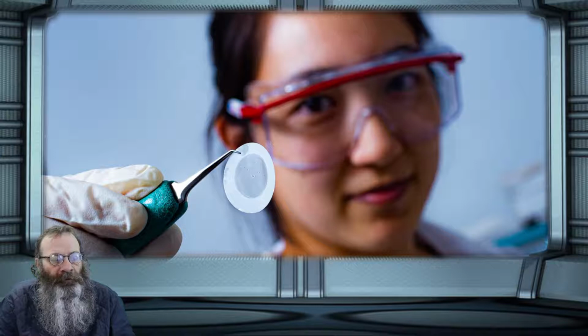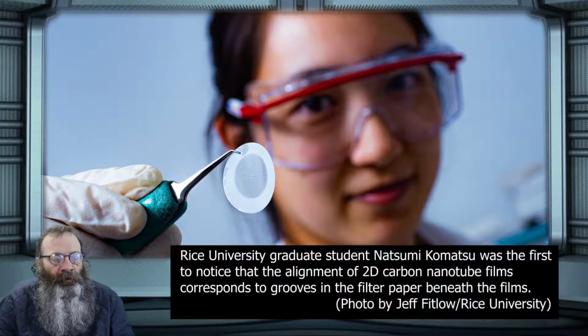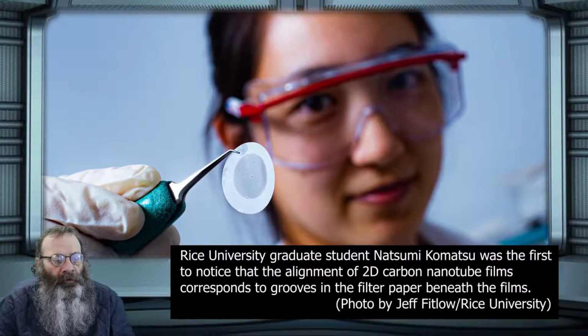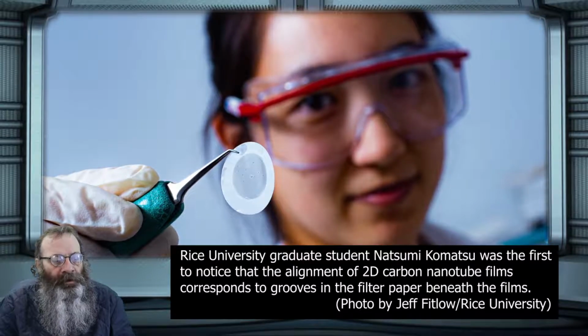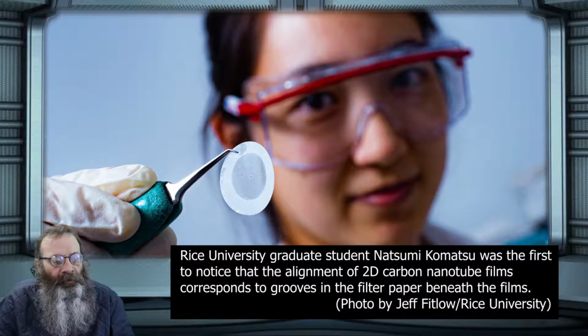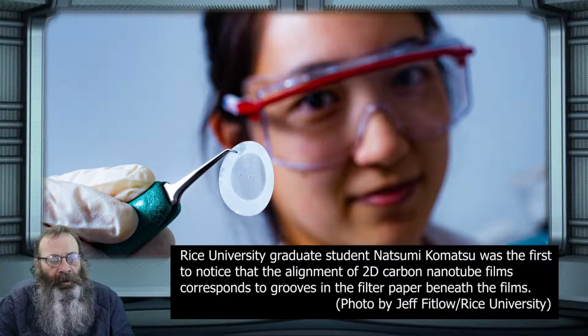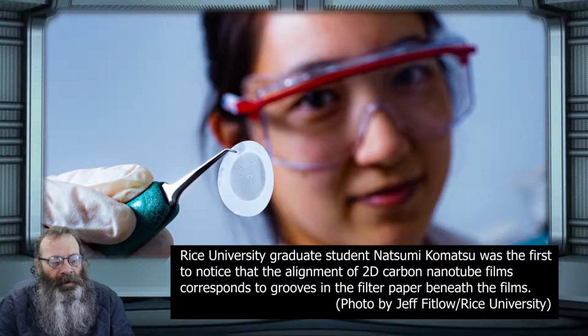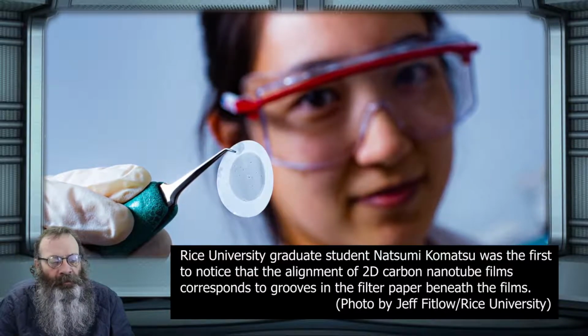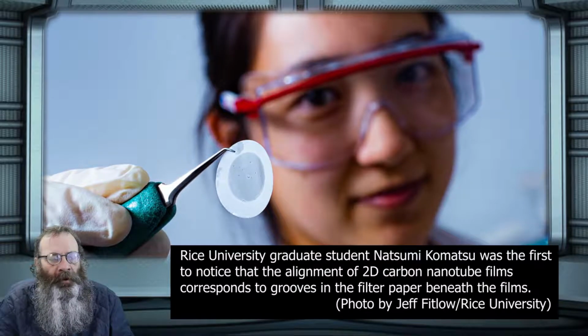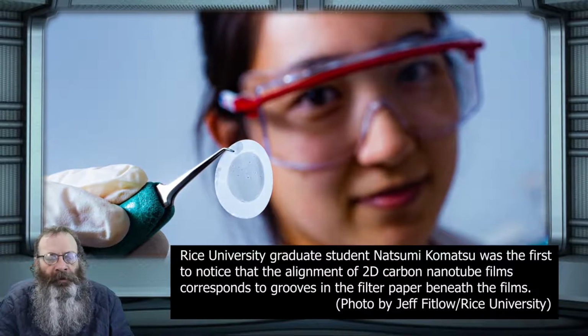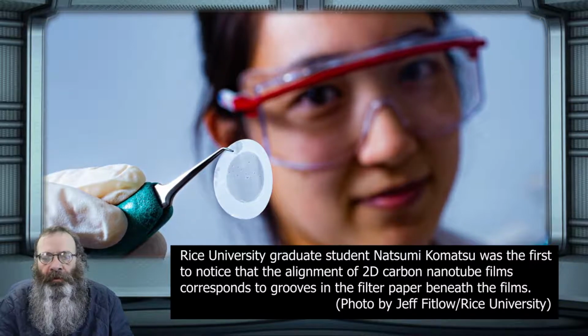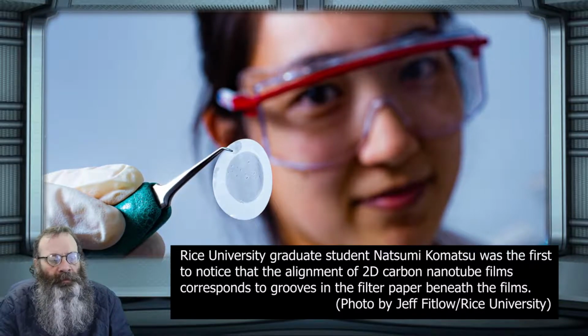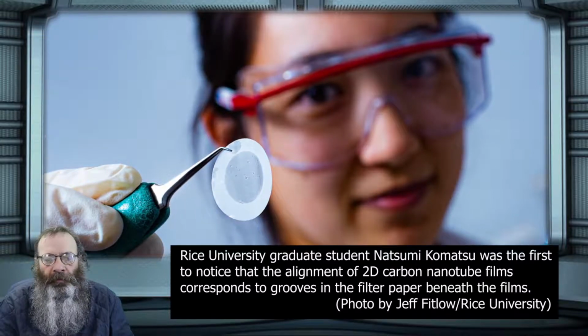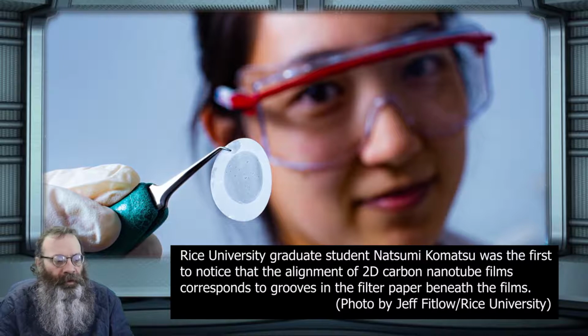To form the 2D crystalline films, researchers first suspend a mixture of nanotubes in a water surfactant solution. The soap-like surfactant coats the nanotubes and acts as a detangler. In 2013, Kono's students were using vacuum filtration to draw these mixtures through membrane filter paper. The liquid passed through the paper membrane, leaving a film of aligned nanotubes on top. In an exhaustive set of experiments, Komatsu and colleagues showed that the alignment of nanotubes in these films corresponded to parallel submicroscopic grooves on the paper. The grooves likely were formed when the filter paper was pulled onto rollers at the factory, Kono said.